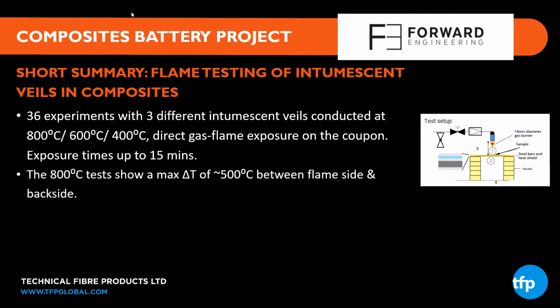Incorporated into composite structures. They were tested at 800, 600, and 400 degrees centigrade with direct gas flame impingement exposure on the coupon. There's a degree of ablation as well as the actual thermal temperature that the parts are seeing. Exposure times of 5 and 15 minutes. And the maximum temperature that was seen on the 800 degrees C test was really about 300 degrees centigrade on the back face. So we're seeing roughly a 500 degrees C insulation value between the flame side and the back side. Next slide, please.